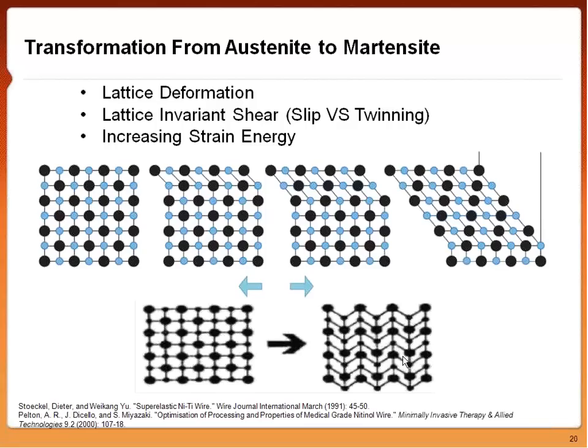Because if we didn't have those two mechanisms working together, if we dumped that piece of nitinol in a cold solution, we'd see it jumble up and bumble together. But in fact, it stays that raw, long bar of nitinol. So what lattice deformation basically is, is small atomic shuffles to move from one crystal structure to the next. Now, again, if that was the only part of the transformation within nitinol, we would see one structure change shape in front of our eyes as we cooled it. But the other part of this transformation is the lattice invariant shear.